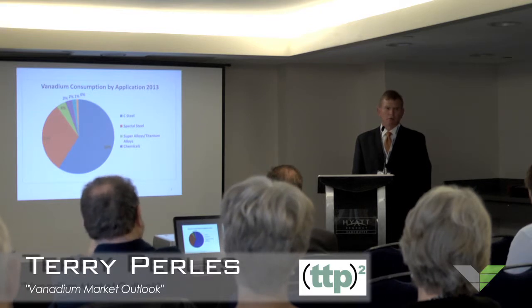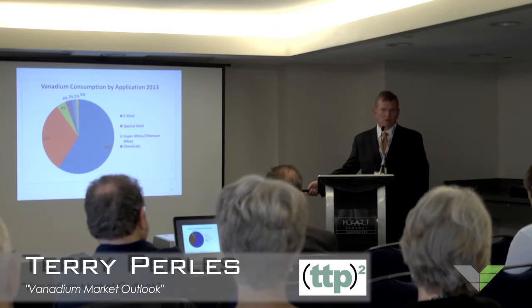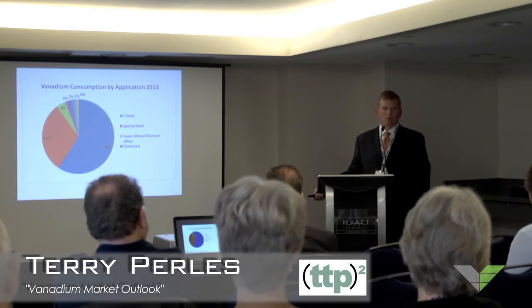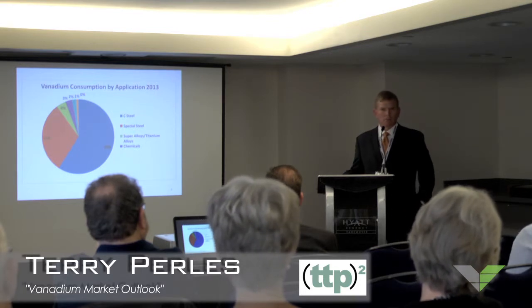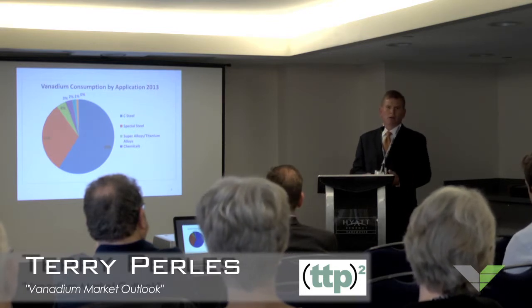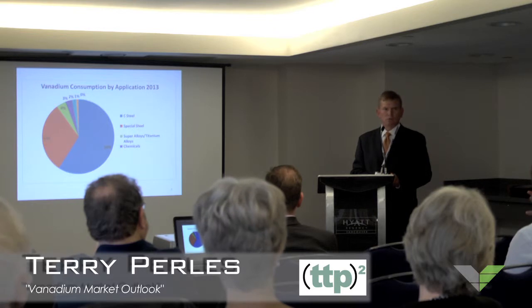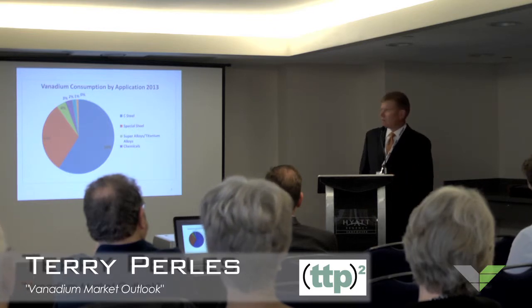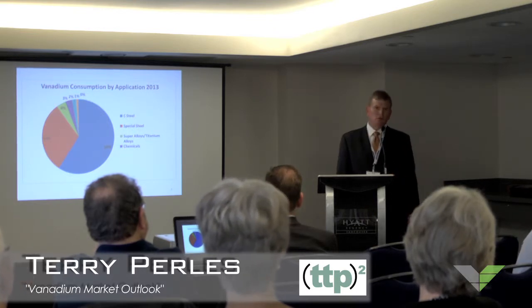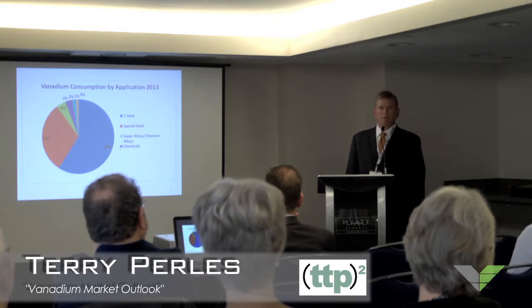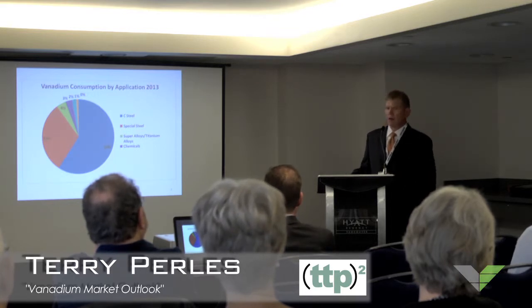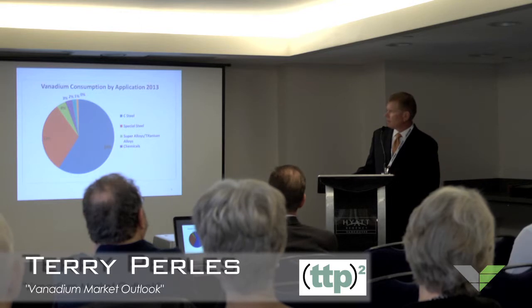They've maximized the utilization of scrap. When they melt scrap, the vanadium comes back into the melt. But the amount of scrap that's available is being depleted now, and as they go forward, they'll be melting more virgin titanium and vanadium master alloys to produce this. So we could envision vanadium consumption in the titanium industry doubling in the next 5 years. So that certainly can have an impact on the market.